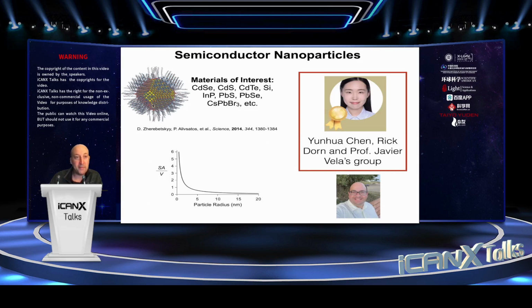So you're going to have this inorganic core with these organic ligands that terminate the surface. You need the ligands to impart colloidal stability to these materials and also to prevent the inorganic cores from reaggregating and just forming larger particles.